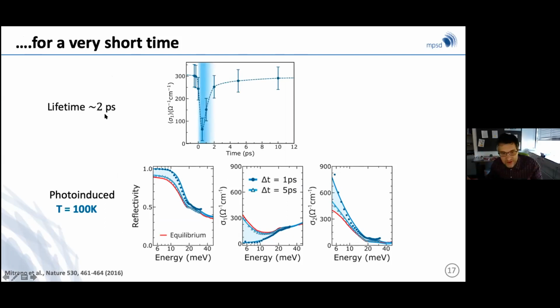So this is all great. You have a high temperature state, which nevertheless only lives for a very short time. If I plot again the integral of sigma 1 as a function of time, which is a large number at negative time delays when the material is a metal, it goes close to 0 after the material is excited. I find a state that lives only for a very short time. When I stop pumping it, it disappears, indicative of a state that doesn't have intrinsic rigidity. Basically, it only works by virtue of the fact that rigidity is being supplied from outside by the drive.